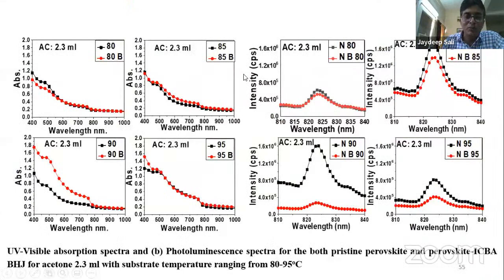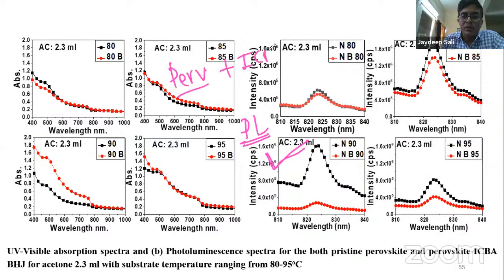I will directly go to the important result, that just by controlling these parameters, what we have got. You can just focus your attention on this one. This is the photoluminescence response of the perovskite film that we have formed. It is a perovskite with ICBA. Here perovskite acts as a donor of charge carriers, ICBA acts as the absorber of the charge carriers. If the charge transfer from the perovskite to the ICBA is good, then the photoluminescence intensity decreases.